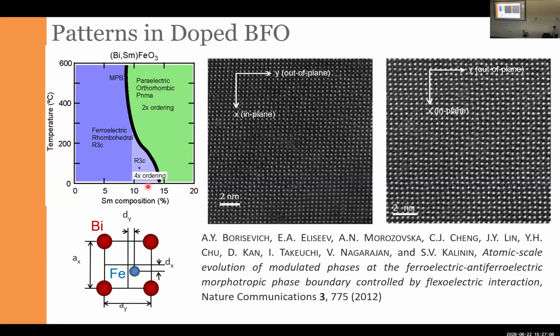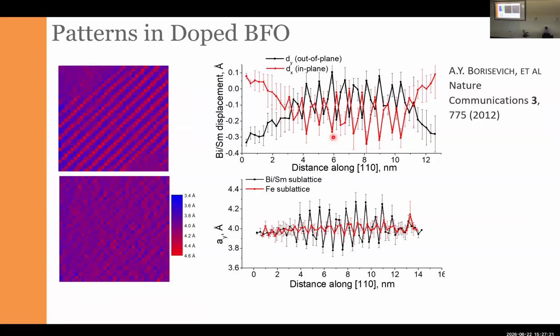And the great thing about electron microscopy is that if you look at this type of sample under the microscope, you can immediately see that something interesting goes on, right? You can see that there is some sort of funny contrast inside these images. If you analyze this data and map polarization and the atomic displacement, you start to see regions where there are no displacements, almost ideal regions where there are no distortions on the level of unit cells.